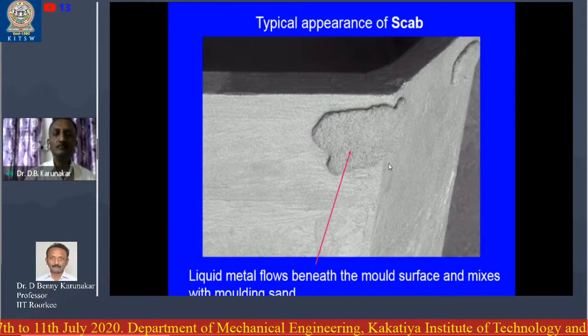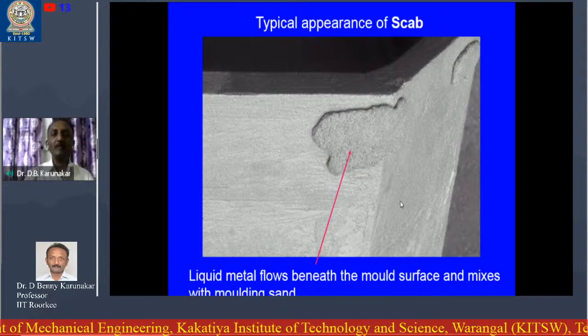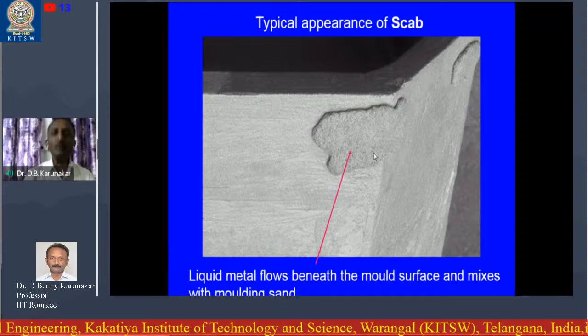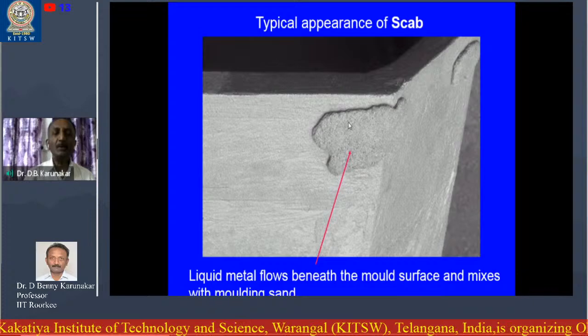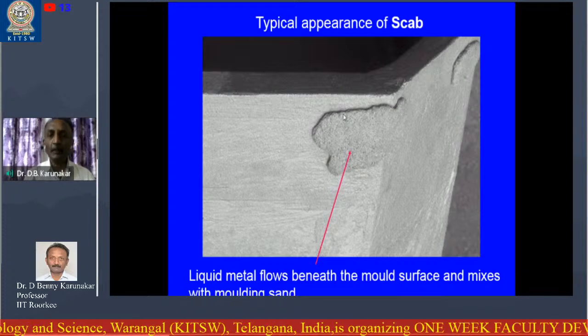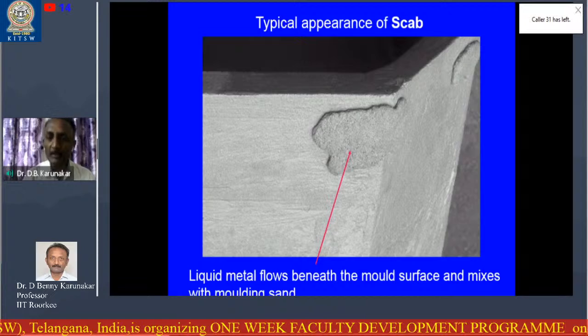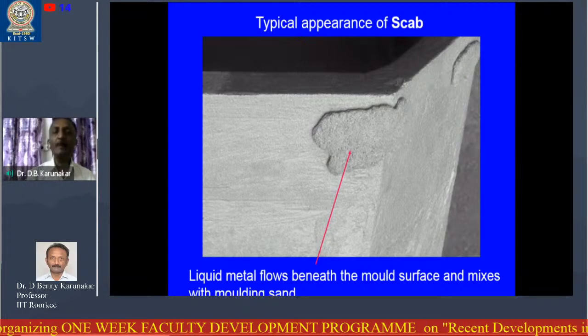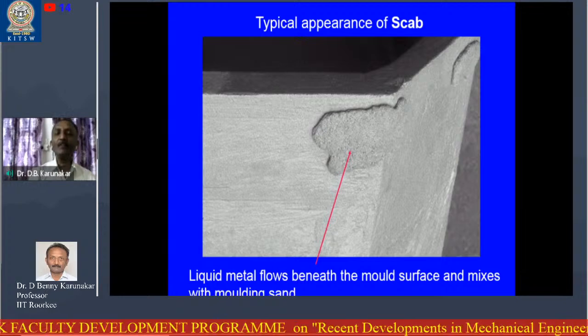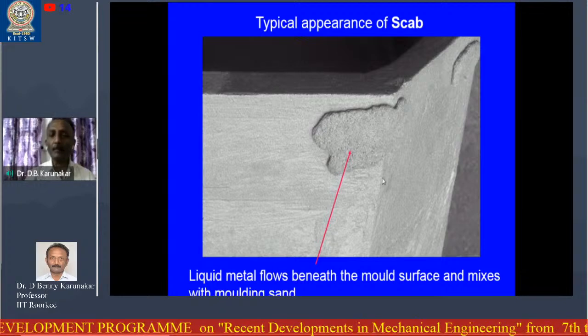So a scab looks like this. This is the surface of the casting, and above it you can see a thick deposition. What is this deposit? This deposit is a mixture of molten metal and molding sand, meaning it has become a hard ceramic lump deposited on the surface of the casting.